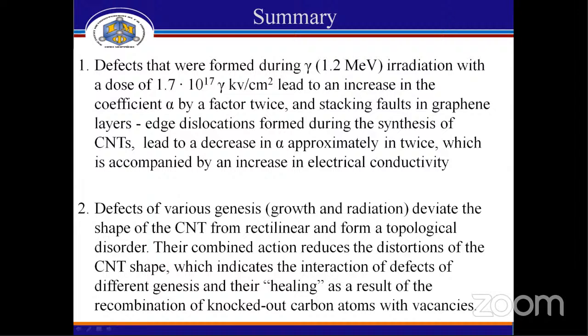Gamma irradiation with a dose of 1.7 times 10 to the 17 gamma quanta per centimeter squared leads to an increase in the coefficient alpha by a factor of two and stacking faults in graphene layers. Defects of various genesis, growth, and irradiation deviate the shape of the CNT from rectilinear and form a topological disorder.